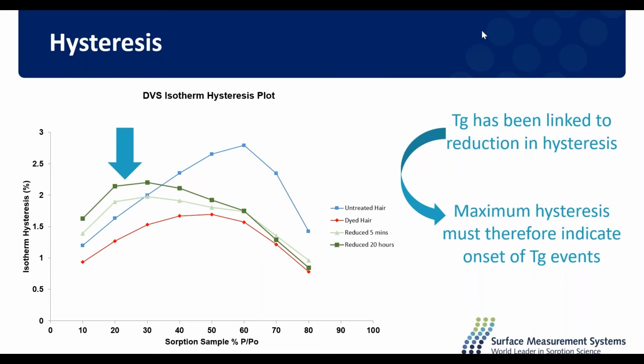Well, as we described before, the glass transition of a polymer is linked to a reduction in hysteresis. That's been shown many times. So we can consider that the maximum hysteresis, the point of maximum hysteresis, must indicate the onset of glass transition events, where any more glass transition events reduces that magnitude of hysteresis, as we see here. So what this is saying for us is that those reduced crosslinks hair samples are having an earlier onset of glass transition events in comparison to the untreated hair.